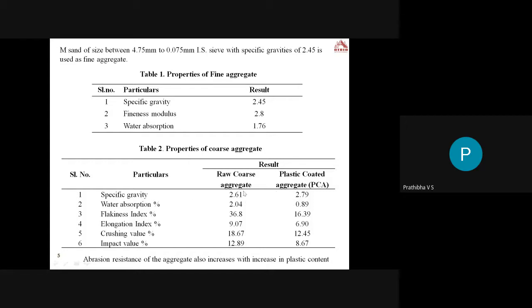The specific gravity of the raw coarse aggregate is 2.61, whereas for PCA it is 2.79. Water absorption is 2.04 for raw aggregate, whereas it is reduced in the plastic coated aggregate to 0.89. Coming to the crushing value and impact value, the major aim of incorporating plastic coated aggregate in concrete is to make the aggregate more resistant to crushing load and impact load. Here we can see the crushing value and impact value are reduced much more in the plastic coated aggregate, which offers more